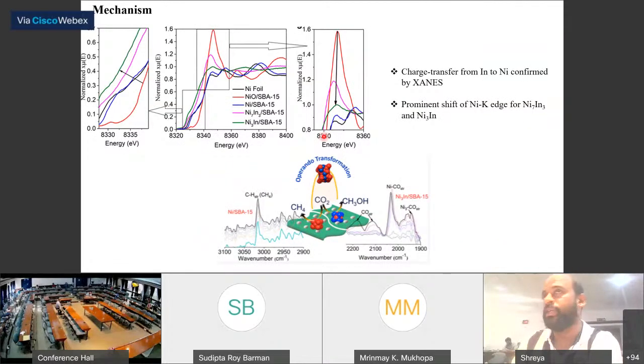So what we have done is XPS analysis, DFT calculations, and in addition we have done XAFS at the PETRA, beamline P65, and you can see that there is a charge transfer. There is quite a difference in the absorption energy and then the XANES data. There is a charge transfer from indium to nickel confirmed by XANES, as you see here. And the white line intensity is also going down.